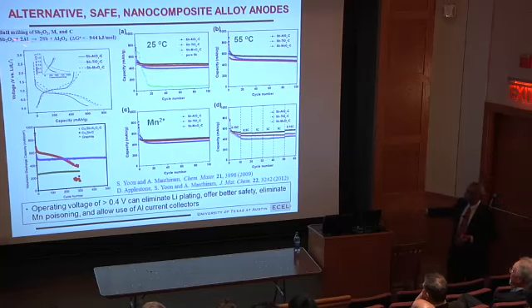You take antimony oxide, aluminum metal, plus carbon, and ball mill. The free energy change for that reaction is negative. So at room temperature ball milling, antimony oxide is reduced to antimony, aluminum grabs the oxygen and becomes aluminum oxide. So you start with this, no heating, nothing, room temperature ball milling, and you get what you need: antimony dispersed in a matrix of aluminum oxide and carbon. Then you get all these cyclabilities.